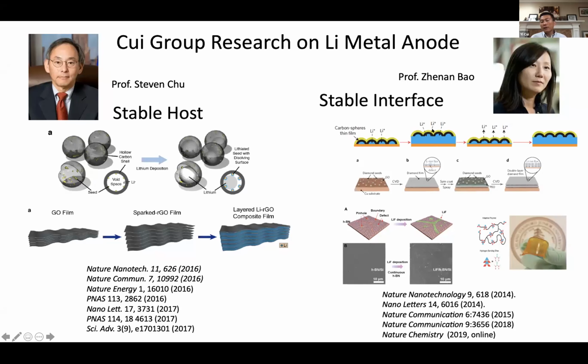Also, a stable interface to control the chemical reactivity is very important. This interface needs to be chemically stable and mechanically resilient. And we have come up with a number of different strategies for how to form the interface, whether it's an inorganic coating or a new type of organic polymer. This is not a finished task, still going. Both of them are still going. And let me share with you some of the key findings right here.